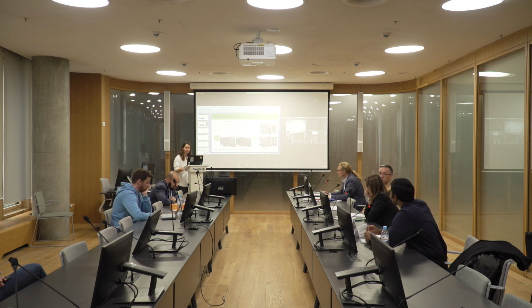Okay, so you did not observe any stable crack growth regime. Like in this image, we see the formation of the crack here, and this is the propagation zone, and the last stage. But it takes about half of the sample, so it's huge in comparison with the other fatigue testing. Okay. So 47. Can you go to slide 47?